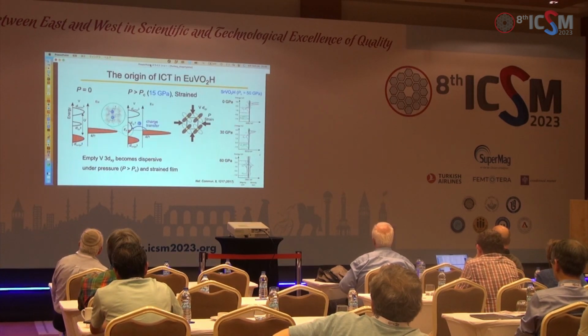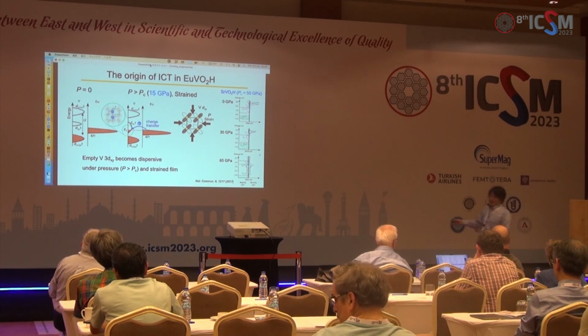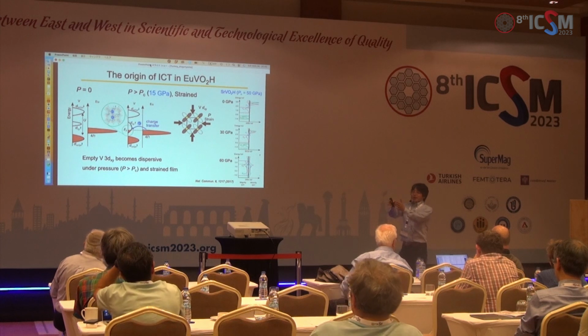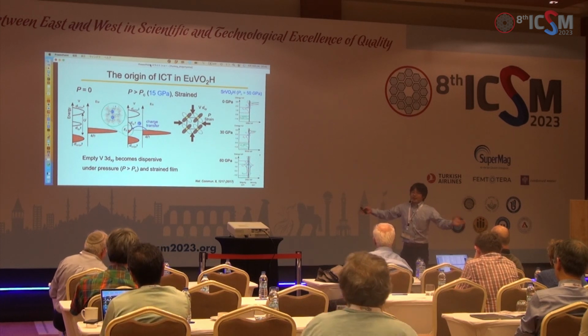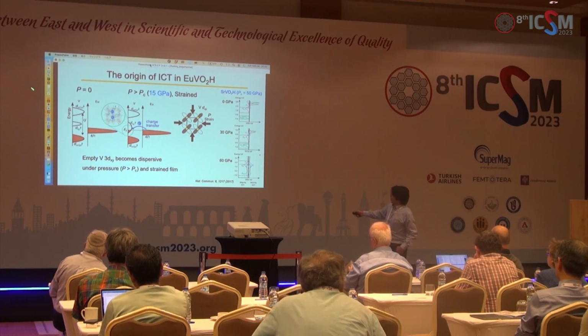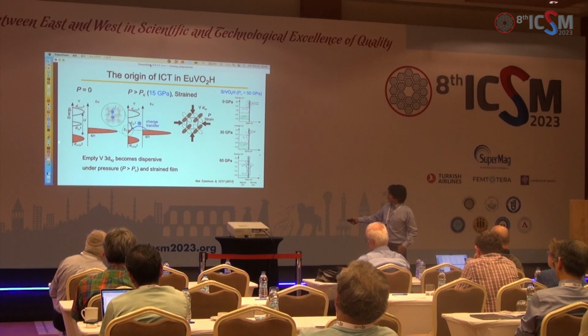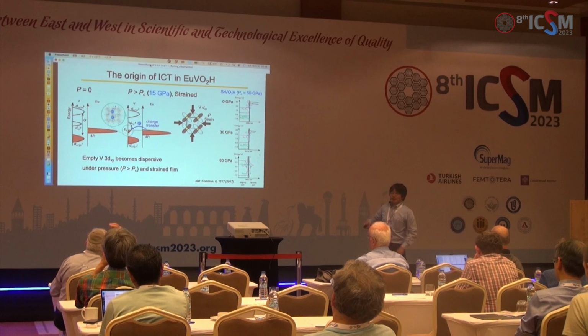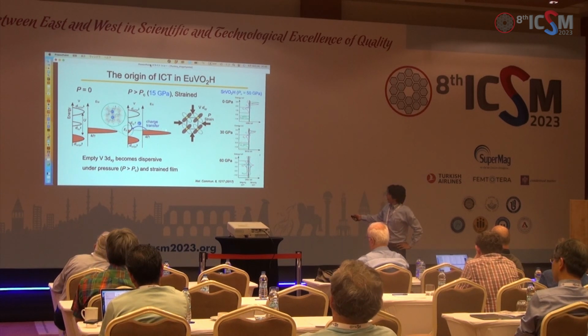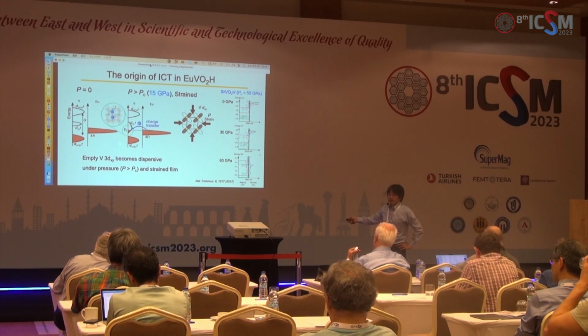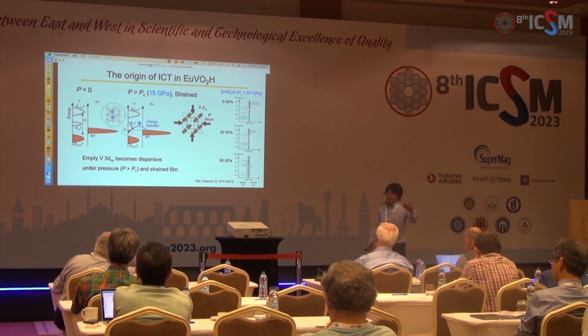Yeah, we have the same stoichiometry in this material, of course. So we are just changing the pressure or applying strain. Then, compared with the ambient pressure phase, as you can see here, you can change the dispersions. Then there is charge transfer from Eu to vanadium species, so the vanadium valence is smaller than expected.